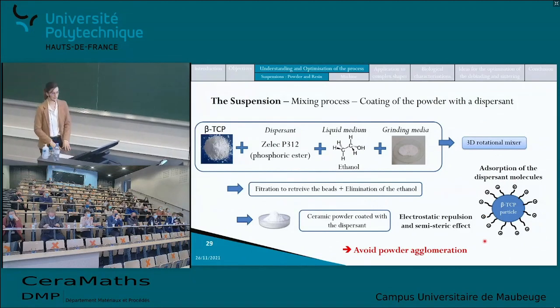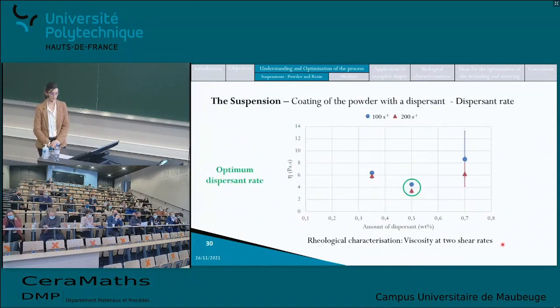I tested 3 different rates of dispersant in the mixture, 0.35 weight percent, 0.5, and 0.7, and I measured the rheological behavior of each of the suspensions at 2 different shear rates, 100 reciprocal second and 200 reciprocal second. And here it appears that the suspension made with 0.5 weight percent of dispersant was the one providing the lowest viscosity, which was what I was looking for. So this was the optimum dispersant rate to be used for my following experiments.